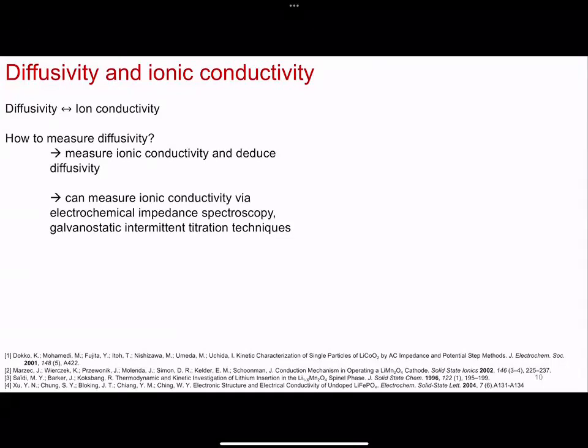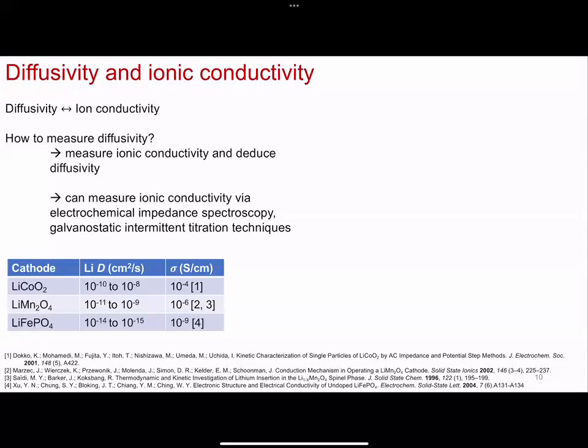You can use a number of electrochemical methods, right? You can use electrochemical impedance spectroscopy. You can use titration techniques, potentiostatic or galvanostatic intermittent titration techniques, to get out the diffusion coefficient or the diffusivity. And people have done that, right? So here are some select papers that have measured these values. You could see the diffusivity of lithium in lithium cobalt oxide, lithium manganese oxide, and lithium iron phosphate. And you could see that for lithium iron phosphate, the diffusion coefficient is really low, right?